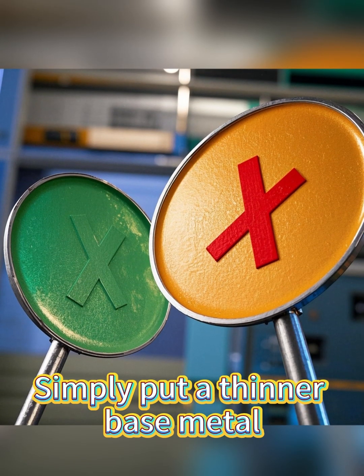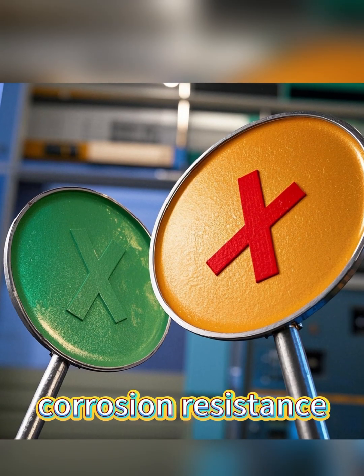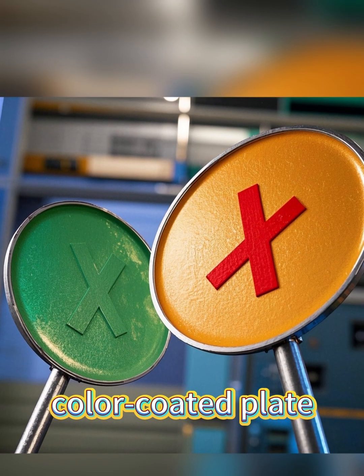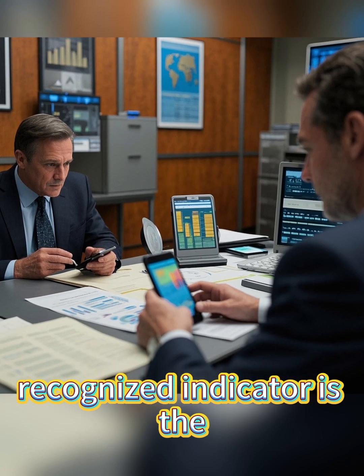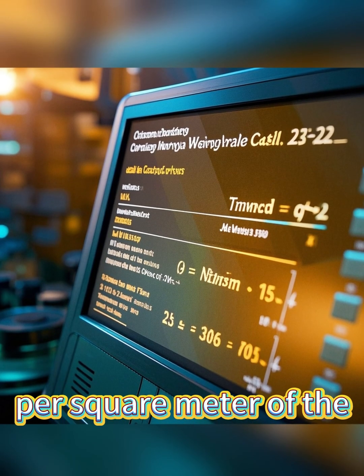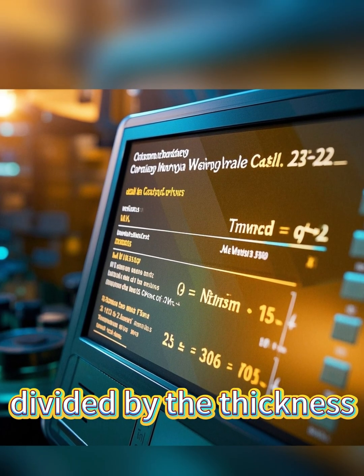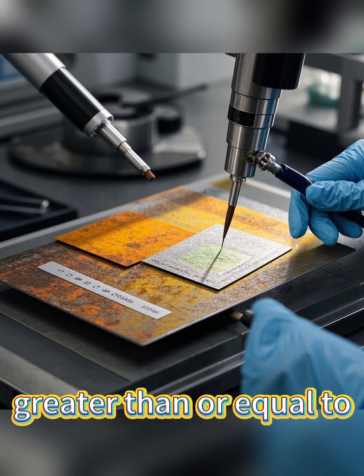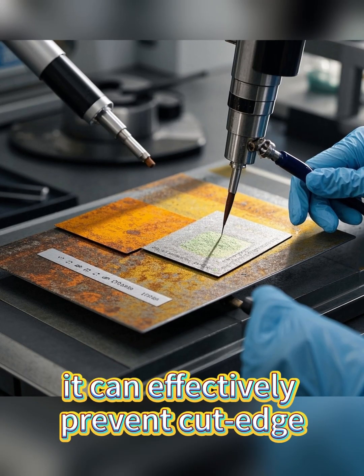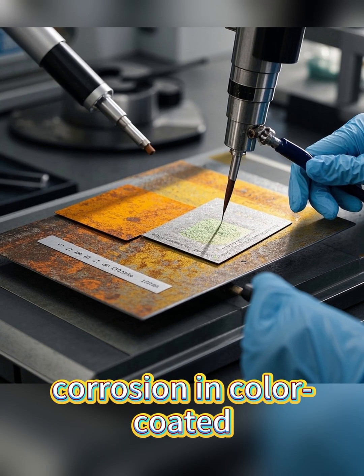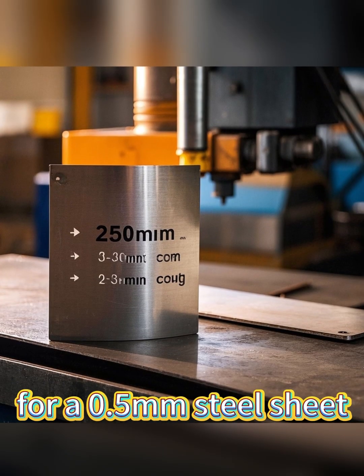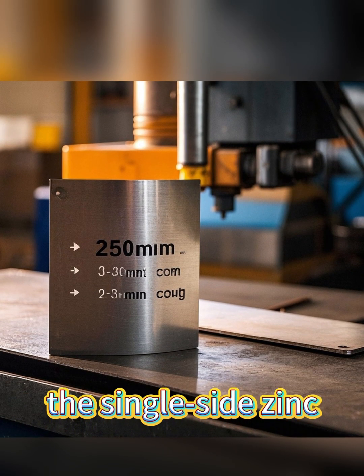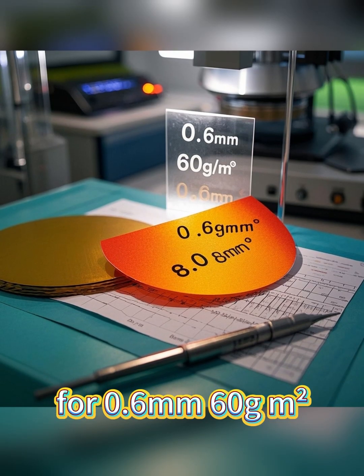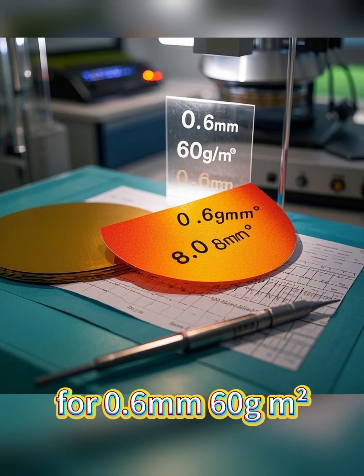Simply put, a thinner base metal and a thicker coating generally lead to better corrosion resistance at the cut edges of the color-coated plate. An internationally recognized indicator is the zinc-to-thickness ratio, which is the grams per square meter of the coating weight per side divided by the thickness of the base metal. When this ratio is greater than or equal to 100, it can effectively prevent cut-edge corrosion in color-coated steel sheets. For example, for a 0.5 mm steel sheet, the single-side zinc coating should reach at least 50 grams per square meter. For 0.6 mm, 60 grams per square meter, and for 0.8 mm, 80 grams per square meter.